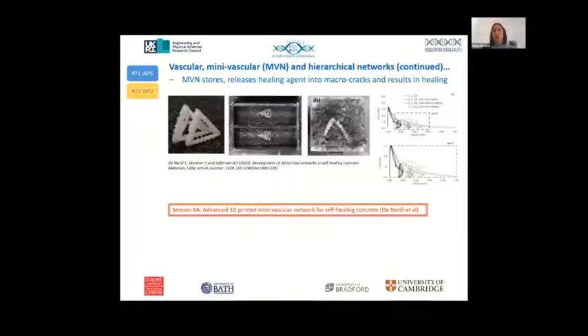To overcome some of the problems that we've had with this release of healing agents, we've looked at developing some novel mini vascular networks, as you see them on the screen. These are 3D printed tetrahedral units. And the notion is that when a crack is formed, it cuts through two of the ligaments. And as such, there's sufficient driving force to drive that healing agent out into the crack. Now, again, we've had quite good success with cycles of this healing using something traditional like a sodium silicate.